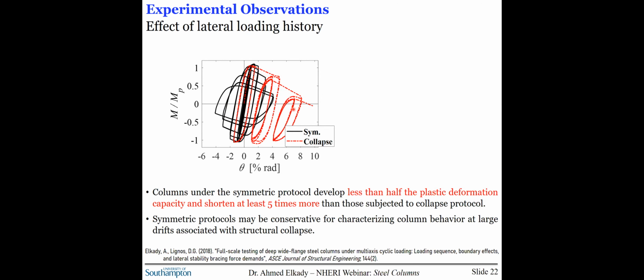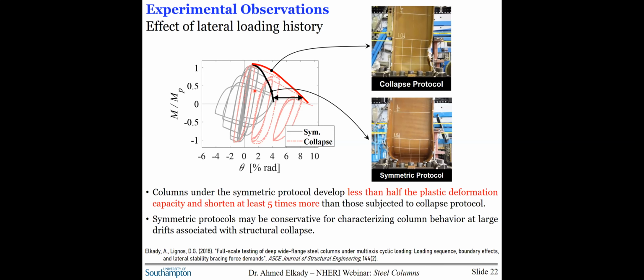To further demonstrate the effect of the loading history, you can see here the different responses of an identical column under the symmetric and the collapse consistent protocols. And you probably can see the difference here. Basically, due to the large number of inelastic cycles of the typical symmetric cyclic protocol, damage progresses faster in this case. And to quantify things, you will see that columns under the symmetric loading protocol develop less than half the plastic rotation capacity and shorten at least 5 times more compared to those subjected to the collapse protocol, which tells you that symmetric protocols may actually be conservative for characterizing column behavior at large drifts associated with structure collapse at large seismic intensities.